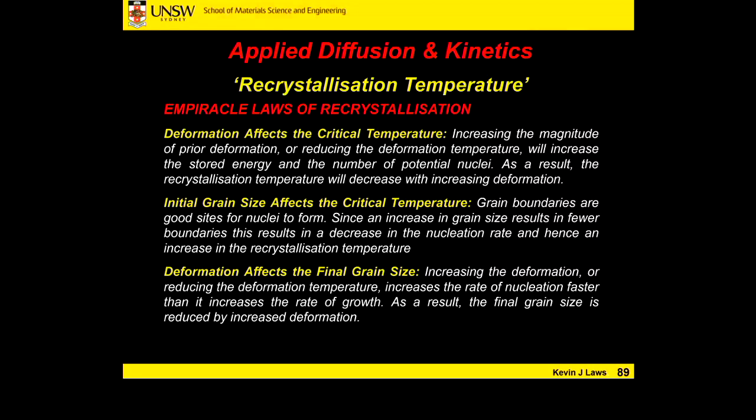Finer grain size material still has a higher degree of internal energy or structural energy than a large grain size material. So our end materials, something that's had a small deformation compared to a large deformation, after the recrystallization process, the one that had the higher deformation will have a smaller grain size and probably higher strength and lower ductility.